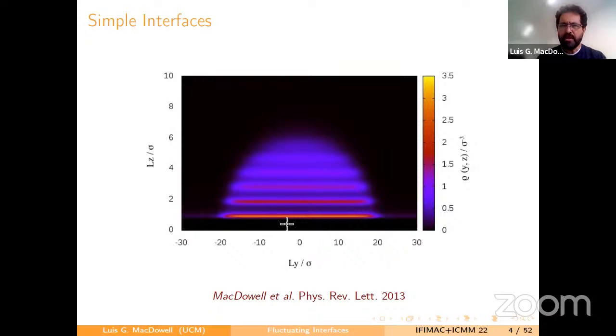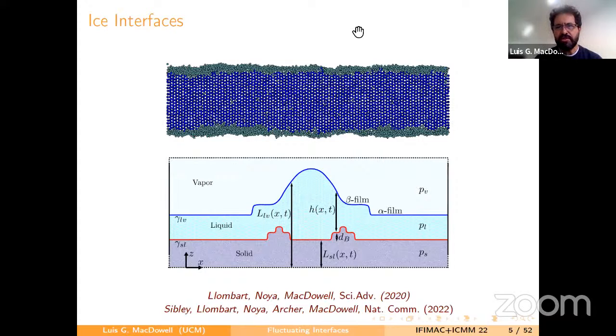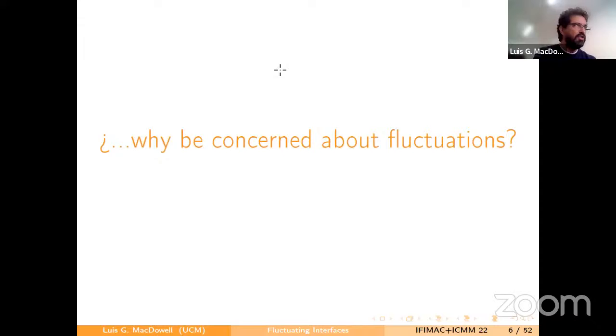I will then move into a somewhat more complex interface, which is the interface of ice with its own vapor. So essentially, the interface of ice in vacuum, which close enough to the melting point is more complex than expected, because you get a layer of pre-melted ice. The first few layers of ice at the interface melt, and as you will see in the next few slides, this gives rather complex and unexpected behavior. So those are the interfaces that I will be talking about, but I will be trying to get rather general information from them. So the results are not really specific to those systems, particularly the first one.